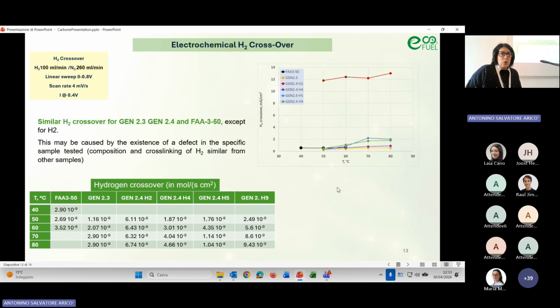In addition, we also studied the hydrogen crossover, because hydrogen is produced and we want to avoid that it comes into the oxygen stream. So hydrogen crossover was also measured by preparing an MEA, like in a fuel cell mode, feeding hydrogen and nitrogen, and using a linear sweep to oxidize the hydrogen that migrates to the nitrogen side. This is the graph reporting the data, and we can see that in general the hydrogen crossover is in the same order of magnitude for the Hydrolyte membrane and Fumatech membrane, that is 10 to minus 9 mole per second square centimeter. But generally, it corresponds to what is reported in literature for polyaromatic membranes, both in protonic or anionic environment.